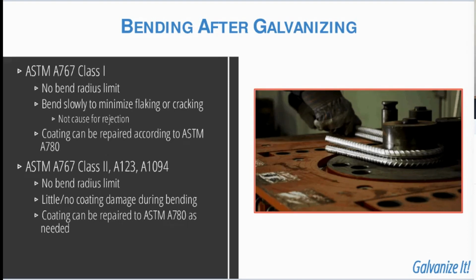If you are bending rebar after hot dip galvanizing, you do not have to worry about a minimum bend radius. That is because you've already exposed the rebar to the heat of the galvanizing process. However, for ASTM A767 Class 1 coatings, which are a bit thicker coatings, cracking and flaking of the galvanized coating at the bend area may be an occasional occurrence, but generally the hot dip galvanized coating is better maintained at slower bend speeds. If some cracking or flaking of the coating does occur in the bend area when bending after galvanizing, this isn't a cause for rejection, and that coating in that area can be readily repaired.